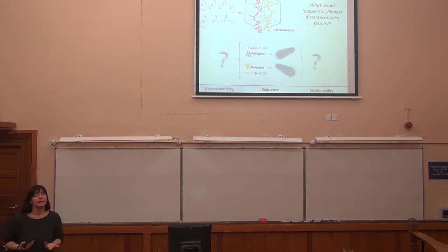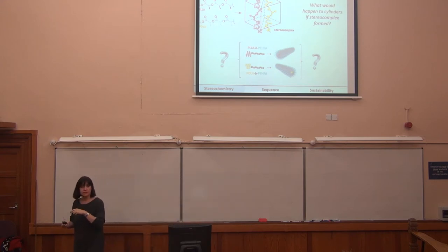But one of the neat things with polylactide is actually if you take the L and D isomer, which I said are opposite helices, if you co-assemble them, you form a stereo complex. And stereo complexes are very interesting. A PLLA stereo complex actually has very similar material properties to polystyrene, so it could be an excellent bio-renewable alternative to polystyrene. But we were quite interested from an assembly perspective in what might be formed if we took D and L together, mixing them either as pre-assembled cylinders or just as polymers.